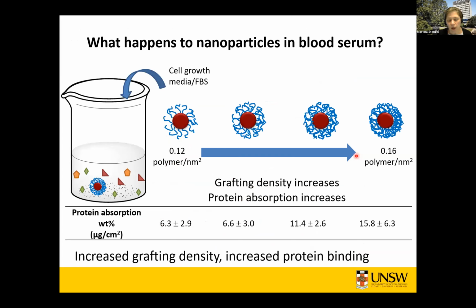And so one way of doing that is that you take these nanoparticles and you incubate them with either serum or you can incubate them with blood. And then you isolate these nanoparticles and you measure how much protein is on the surface. And what we find is there's really quite a substantial amount of protein on the surface. So this means basically we started off with a nice sugar layer but now we have a layer of protein on the surface. So our targeting ability is reduced.